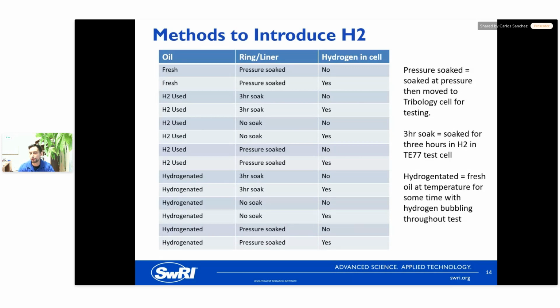I'm not really here to debate all of that, whether it's creating the real case scenario inside the engine. We're just trying to prove whether or not hydrogen itself is going to cause any sort of tribological concerns, and that's what we're trying to replicate here. So you could argue that the case that we're presenting, having it soaked in hydrogen and going through the oil in these very severe cases, isn't the real scenario in the engine. But the main thing is that we're able to recreate those conditions in our test cell. So if that is the case, we can actually set that up here and prove that it will have an effect on your friction and wear performance.